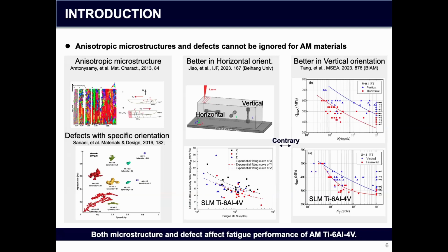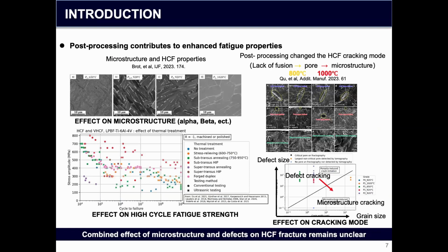For example, we cannot judge directly which direction is better. For the study by Beihang University recently, they found the better direction would be the horizontal orientation. But for the same material from BIAM, they said the vertical orientation would be better. So people also use post-processing to enhance the fatigue properties, because they can change the microstructure and also the defects in the material. But right now, the combined effects of microstructure and defects on high cycle fatigue fracture remain unclear.